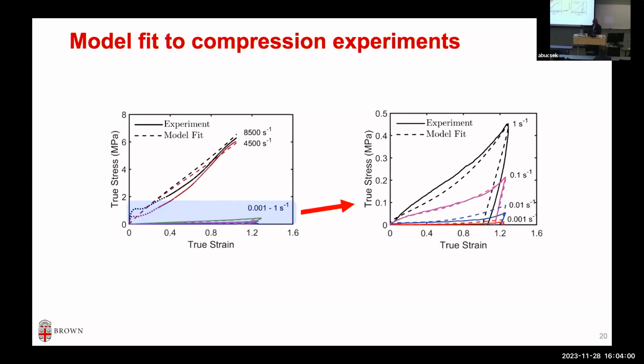And what we had, remember, these one-dimensional stress-strain curves at different strain rates. We can go and calibrate. So you can see these dotted lines are from the model fit, the solid ones are the experiments. You can see the whole wide strain rate range of 7 orders of magnitude with all the non-linearity, loading and unloading as well. We can capture, or calibrate, the model quite well. Right? The model has all the right physics informed, basically a macroscopic scale model that can predict the observed one-dimensional behavior. The model is 3D, right? So we are pretty happy here.